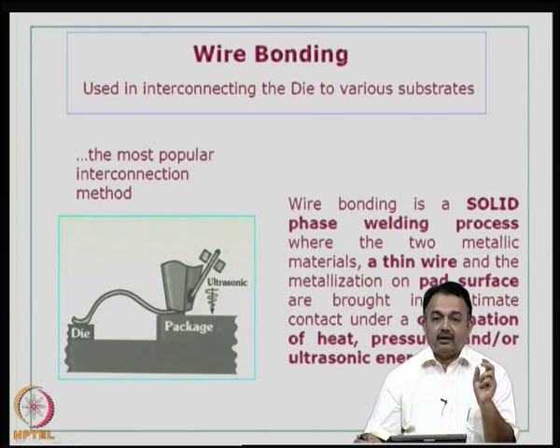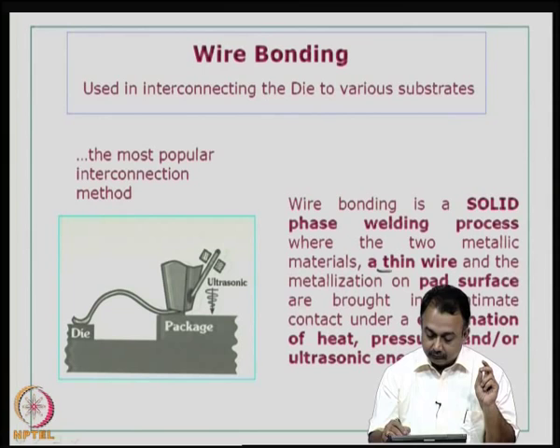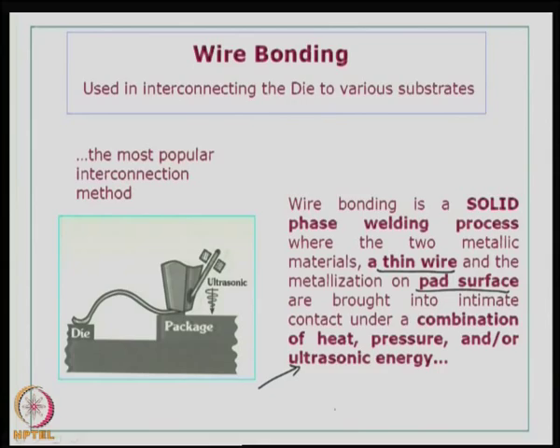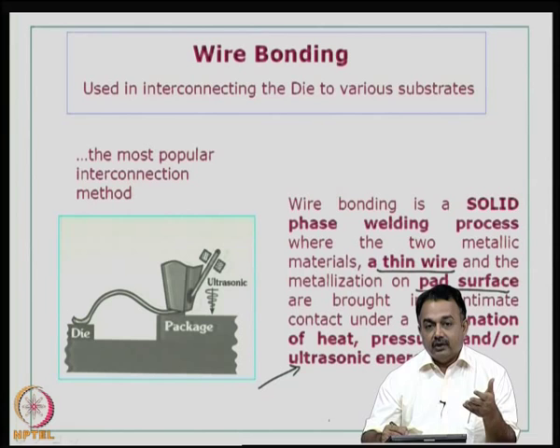On one side you have a thin wire and the other side you have a pad surface ready to take up the wire. These are brought together in intimate contact by the wire bonding process using a combination of heat, pressure, and/or ultrasonic energy. You can decide what combination you want to make the process simpler without providing too much heat that can damage the substrate. Depending upon whether you are using gold, you can use thermocompression bonding; if you are using aluminum, you can lower the temperatures.